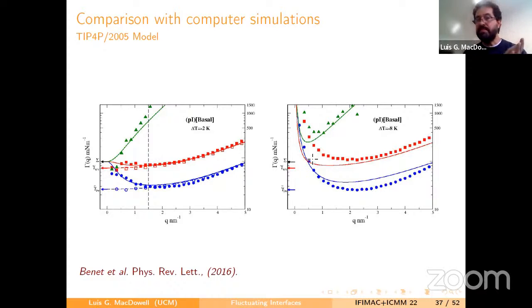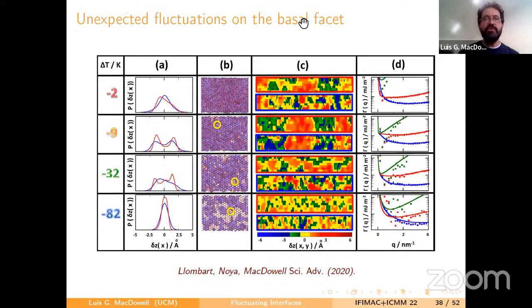So what this means is that the prism facet of ice, in a range between -2 and -8 Kelvin, is undergoing a roughening transition. And what that means is that at this temperature, its growth rate is going to change completely. And we expected this would have some impact on the shape of the crystal habits. Okay, but as we have seen, the Nakaya diagram is actually quite more complicated. And so we also had to study fluctuations on the basal facet. On the basal facet, that is the base of the prism.